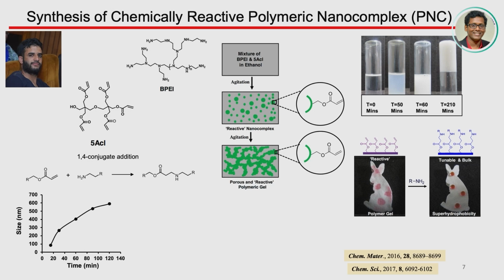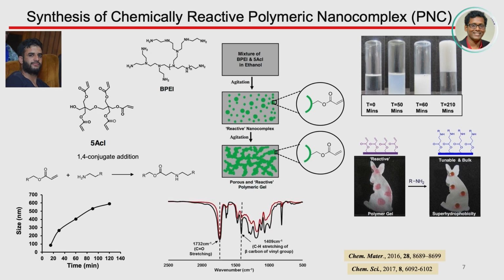And you can see the growth of the reactive nanocomplex, and you can precisely modulate that just by changing the reaction conditions, even the reaction solvents and some additives. We can make it faster or slower, and that's the way we can achieve some of this surface sol-gel chemistry and get the porous coating. I'll come to the next slide and explain that part.